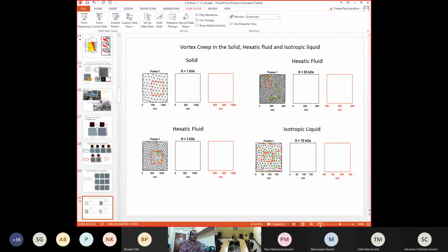I am zooming into this region, and you can see the vortices are moving either in this direction or 60 degrees from it or 120 degrees with respect to this direction. So it is flowing, but it is flowing only along preferential directions. It's clearer here, for example, at 50 kilo Ørsted, if I look at this small region, the vortices are moving along this direction, which is again one principal direction. So this is the equivalent of Brownian motion.